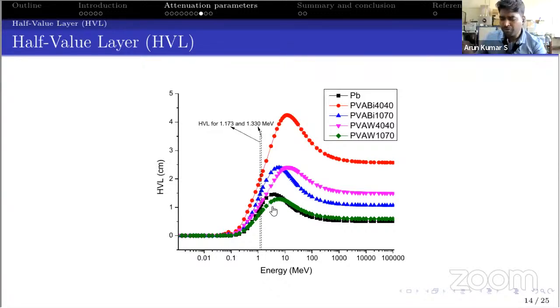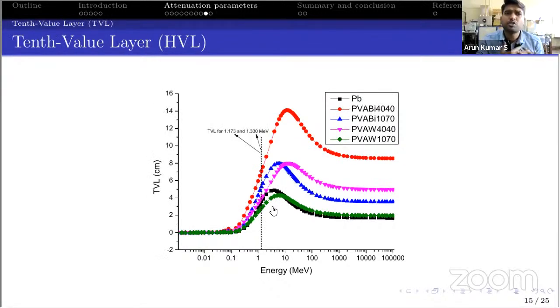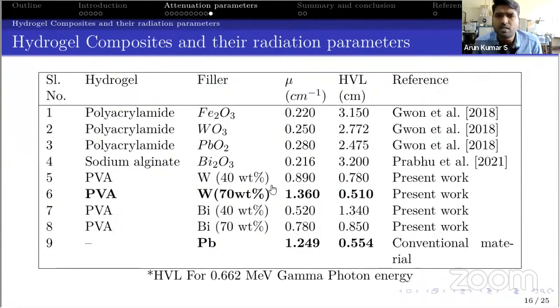Furthermore, here I have tried to measure the tenth value layer of the material. The half value layer is the layer which can reduce the intensity of gamma rays to 50%. Meanwhile, the tenth value layer defines a 10% intensity remaining. Done. So it is clearly showing that the PVA tungsten composite with 40% and 70% filler rate gives very good attenuation when compared to PVA bismuth and lead. Here are certain data which are already published. Here I have taken the 0.662 MeV or 662 keV gamma photon radiation.